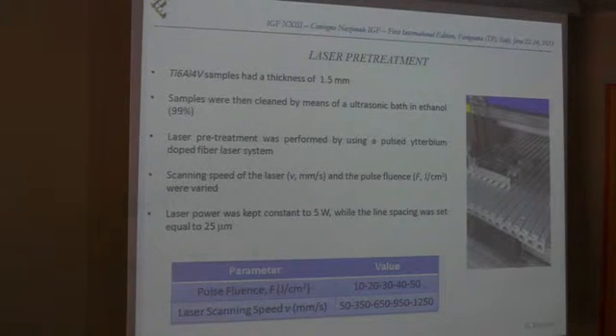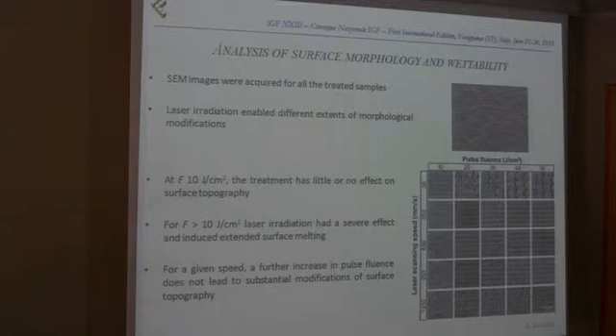From the other side, we varied the scanning speed, so the speed at which the head of the laser was going through the surface, and the pulse fluence. And we changed them within 5 levels, so we had a total of 25 different tests. So the first analysis we performed was the analysis of surface morphology. So we did the SEM imaging, and on the upper part you can see the as received material, and on the other figure you will see the matrix of the treatment.